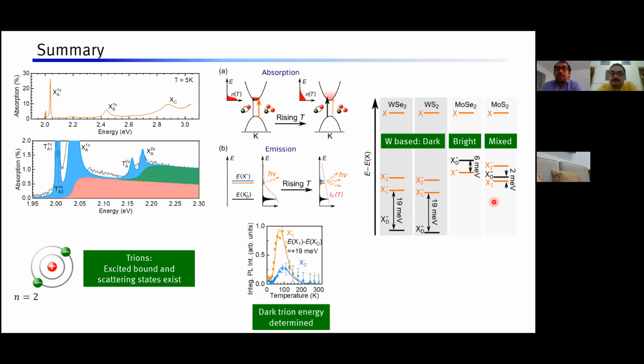So in the lowest order, one can try to look at the conduction bands, the ordering of conduction band splittings, for example, using DFT and performing a GW correction to say how the conduction bands are aligned. Is a dark state favored or a bright state? However, when you add excitonic and trionic effects to that, then you have to do a full-fledged calculation, which Thorsten does, and then it's not so easy to predict without solving the Bethe-Salpeter equation. It's not very intuitive to know which should be bright and which should be dark. This is what I understand.